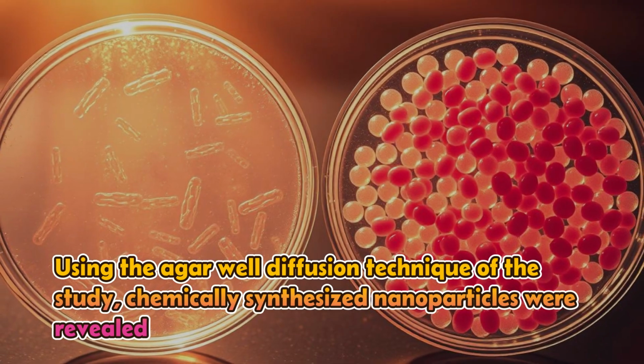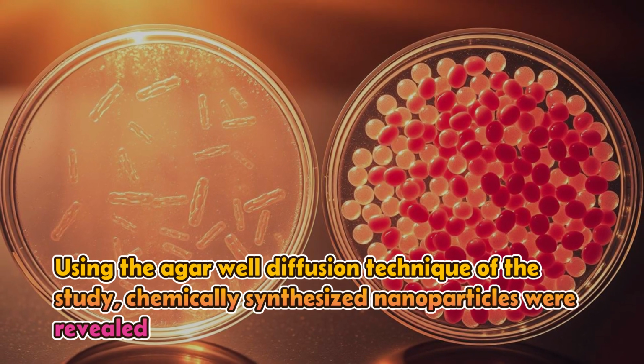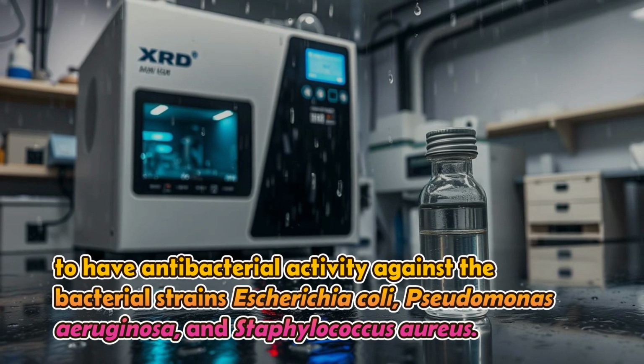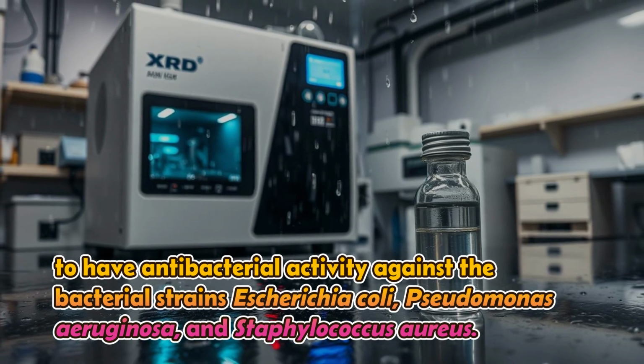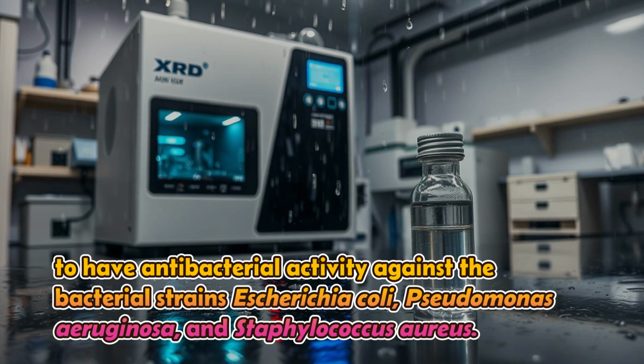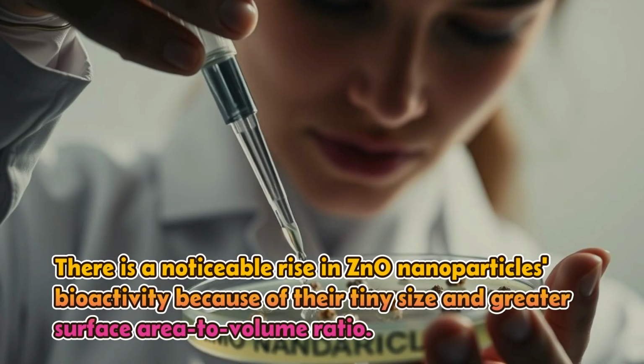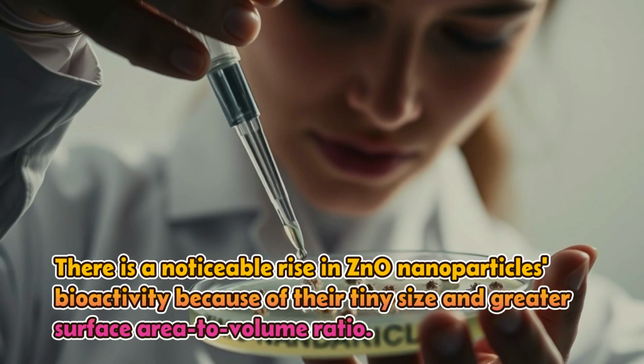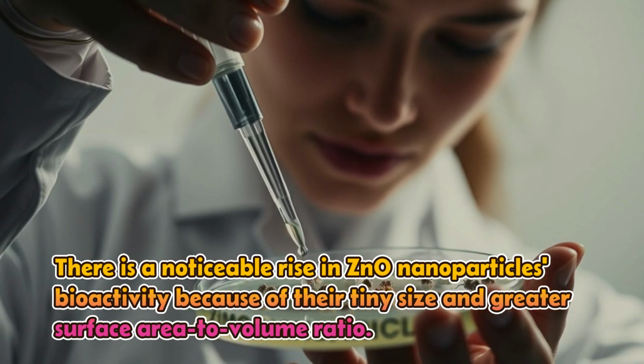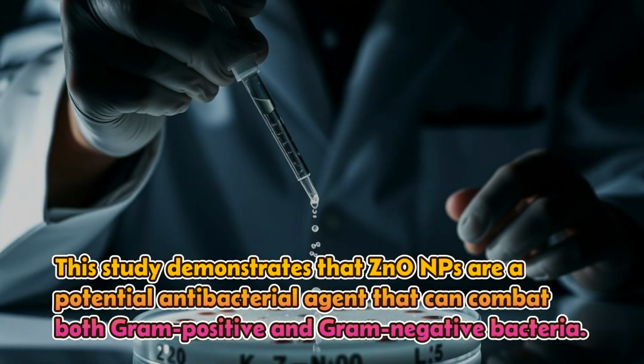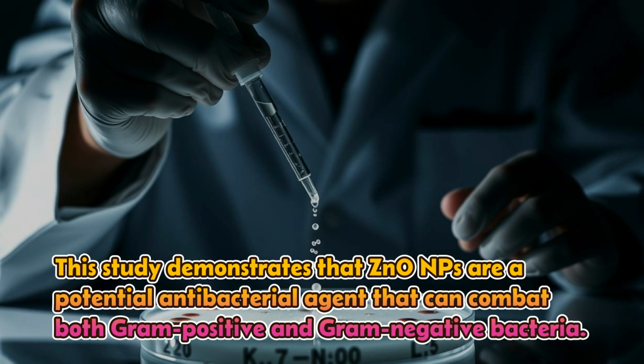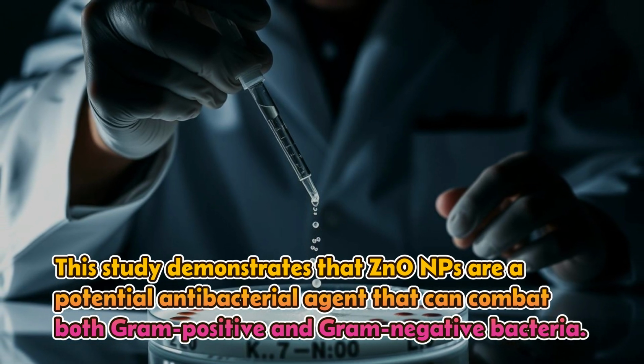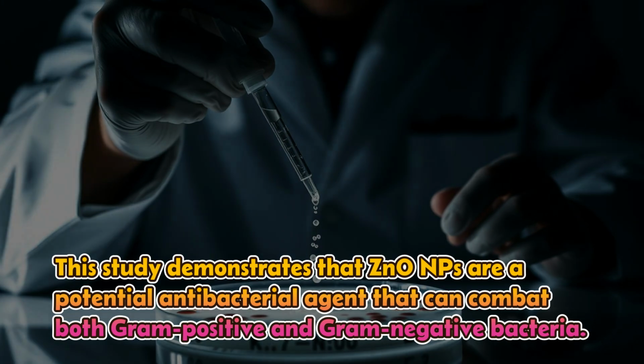Using the agar-well diffusion technique, the chemically synthesized nanoparticles were revealed to have antibacterial activity against the bacterial strains Escherichia coli, Pseudomonas aeruginosa, and Staphylococcus aureus. There is a noticeable rise in ZnO nanoparticles' bioactivity because of their tiny size and greater surface area to volume ratio. This study demonstrates that ZnO NPs are a potential antibacterial agent that can combat both gram-positive and gram-negative bacteria.